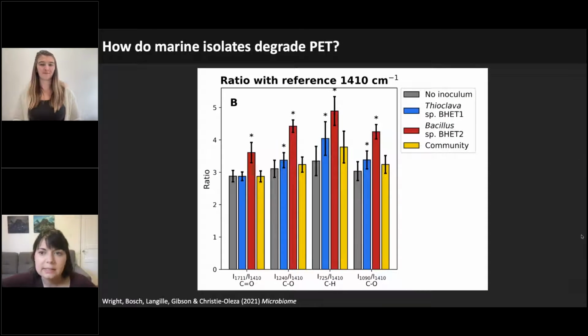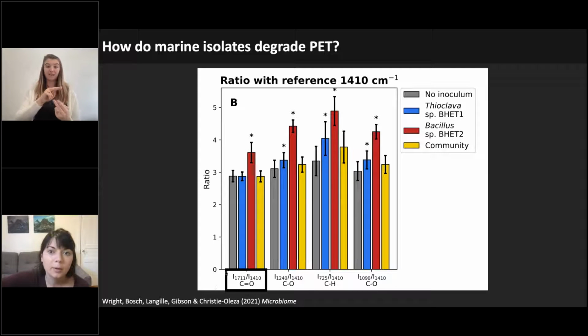So we took a look at the pieces of plastics after they'd been incubated with the isolates and our community, and we used FTIR spectroscopy for this. So very simply, this allows us to look at changes in different chemical bonds or in the structure of the plastics. So for example, an increase in this ratio indicates that we have an increase in the number of carboxylic acid, carbon-oxygen double bonds on the plastic surface, which is indicative of hydrolysis or breakage of the PET chains.